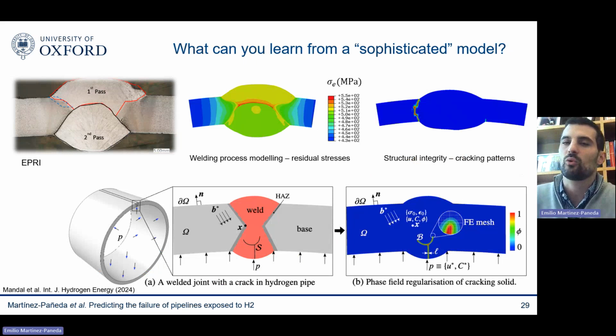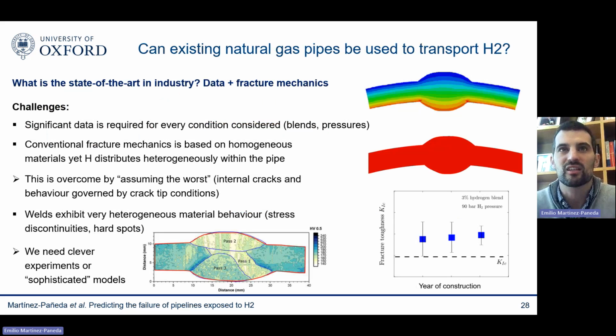So how do these sophisticated models work? Well, it's the same model that I showed you before, but you combine it with some welding process modeling. So you know what the distribution of residual stresses is, you know what the distribution of your phases is, and therefore you know what their toughness distribution is. And again, let me emphasize, the problem that industry is facing is that this works well when you have a homogeneous material. So this works well if you're looking at the integrity of your base material. If you do this approach for the base material, then you're safe.